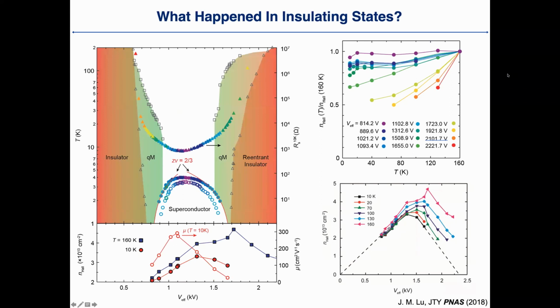And if you measure the carrier density as a function of temperature, you start to see that at high carrier density, at high gate, this carrier density starts to decrease due to this trapping effect. At a low temperature, you cannot even measure the carrier density by Hall effect because the system becomes too insulating.